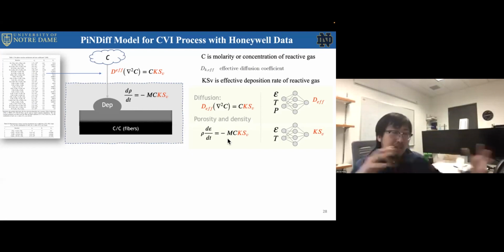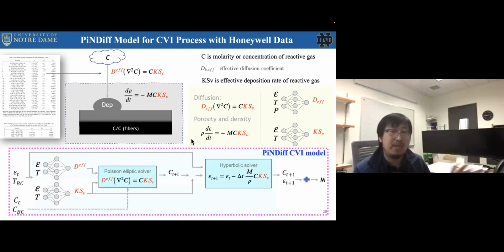We can use operator learning to learn this operator, because this diffusion coefficient is a spatial temporal field. It's going to change over time, and it's related to the porosity field, temperature field, pressure field. Okay, so we can use some neural network to learn the relation between those, basically to learn this operator. Same for the effective deposition, and we can similarly build this CVI model. So in general, the idea is we encode this diffusion process and those hyperbolic PDEs into this module. So basically, this PDE-integrated module will learn the transition of the porosity from time t to time t+1.